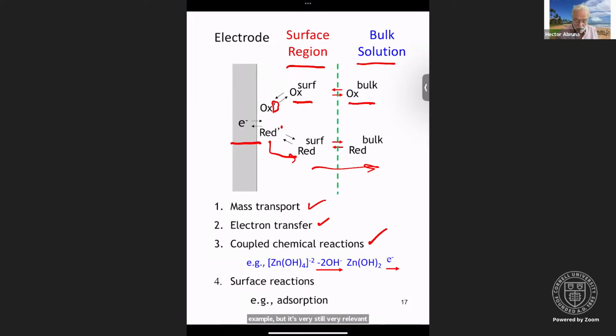Here's a very, very old example, but it's still very relevant. The reduction of zinc in alkaline media: it exists as tetrahydroxyzinc. In terms of the mechanism, it involves the loss of 2 moles of hydroxide. It generates zinc hydroxide, which is actually adsorbed to the electrode surface. You reduce it, and this gives rise to elemental zinc. And this is of great relevance to, for example, zinc air batteries.